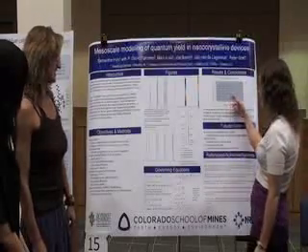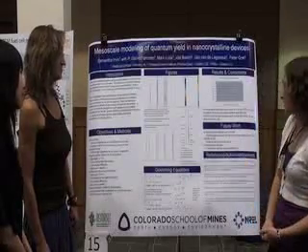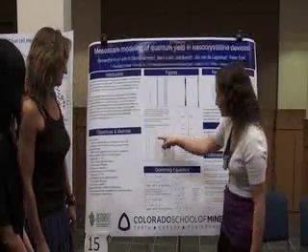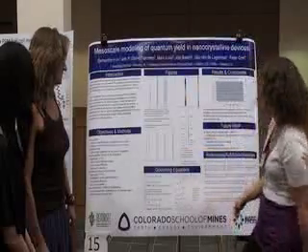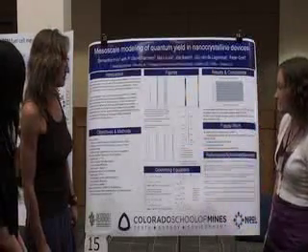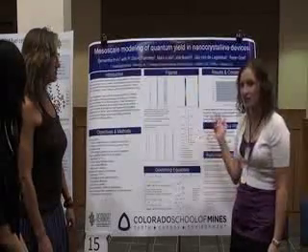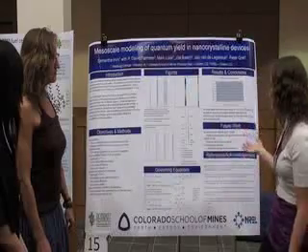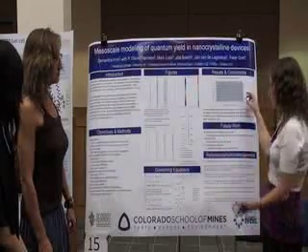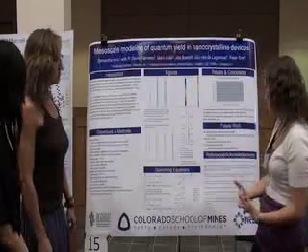They start increasing fairly steadily here, though, starting at a 13.5 nanometer semi-minor axis dot. And we only got up to 22.5 nanometers for our semi-minor axis, because just with the thickness of the i-type layer, that's just the largest size of dot we could get. Well, hopefully, if you were able to make a larger dot, you could see that it would still increase, and then show that, yes, the larger the quantum dot, the better.